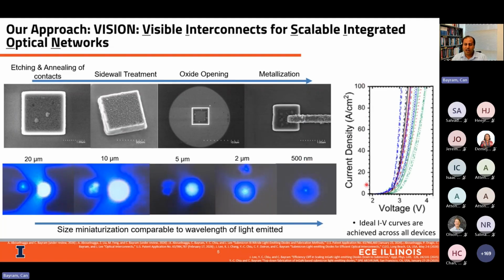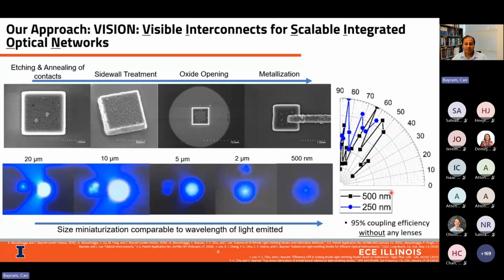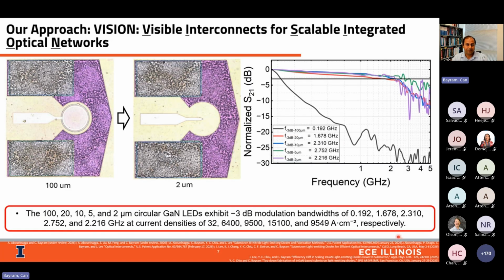And here you can see the IV curves of these scaled devices, which are almost ideal, even for 250 nanometer solutions. Now, what's interesting is, as we scale these light sources, we show increased directivity, which led to a very close to ideal coupling efficiency without any lens, which is a very distinctive feature.